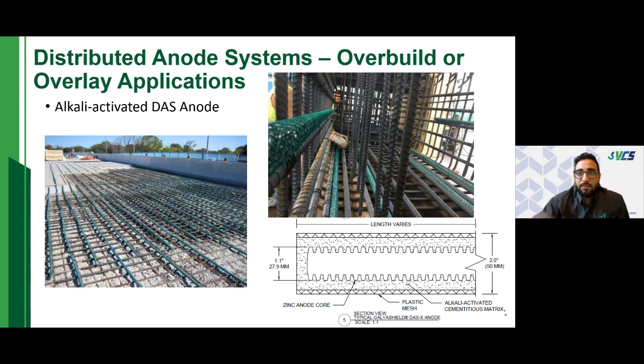For overbuild and overlay applications, they have the mortar-encased regular alkali-activated DAS. You can see in this image the zinc anode core with the grooves on the surface, and that zinc core is encased in a highly alkaline cementitious mortar around it.